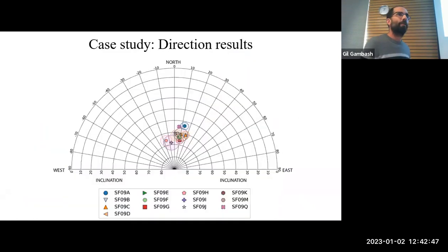So I sampled all of this, and these are the direction results. Unlike Givati parking lot, where I showed we had a few exceptions, here there were no exceptions at all. Everything I sampled here, the collapsed material, the in-situ material, the inside of the bricks, everything gave me the same directions, roughly north and down. Again, you see the scatter is mainly the collapsed material. It gave us directions that are more scattered. And to reconstruct the ancient field, we used only the in-situ bricks that are part of the wall. But for site formation, it's clear-cut here. All this material was clearly heated and cooled down in the orientation in which I sampled it, including the collapsed material.